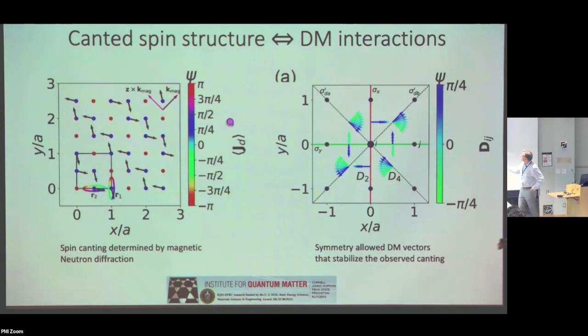And then what he's done is that he asked what kind of DM interactions are needed to stabilize this particular kind of canted structure. And it's quite involved, and you have to take a look at the paper to really assimilate it. But I just wanted to point out that this colored ring reads off the phase angle that comes into specifying the angle that the DM vector makes with the crystal lattice. Because this angle points to this blue-greenish region, that is the orientation of the DM vector that is inferred from this observed experimental structure. So this was how the DM vector and its orientation was established from the experiment.